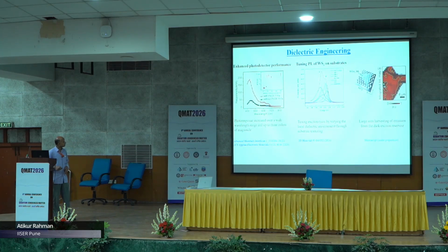Very recently, we showed that by using a different kind of substrate, with a pillar geometry where the pillars are 50 nanometers apart, if you place a WSe2 monolayer, you can harvest this dark exciton over a large area.